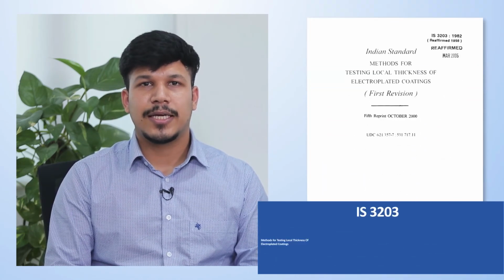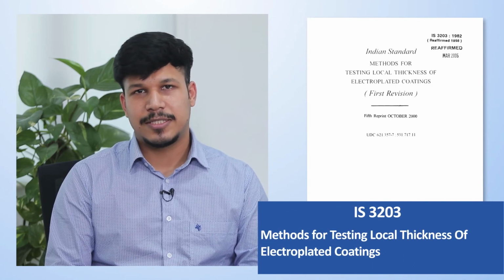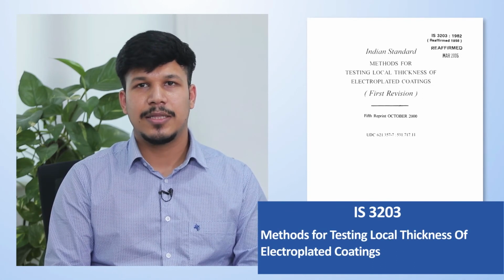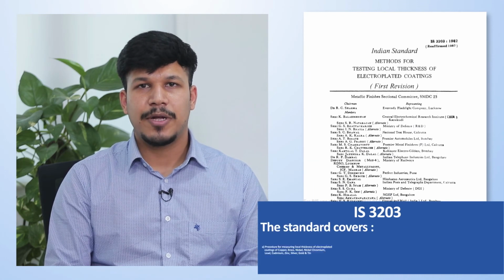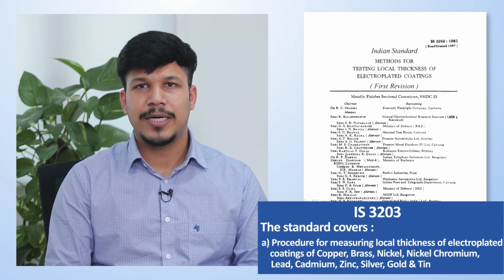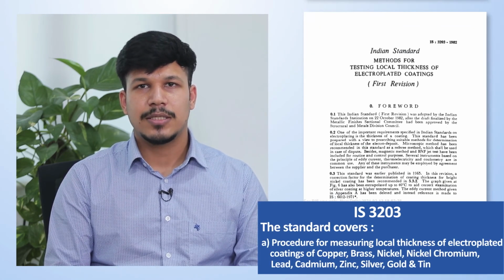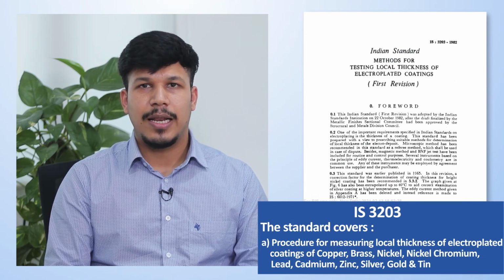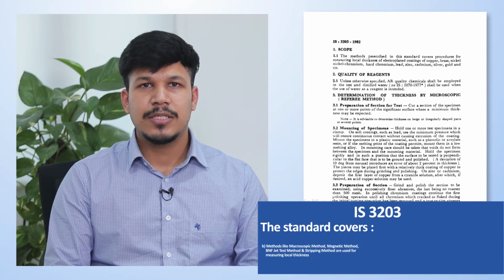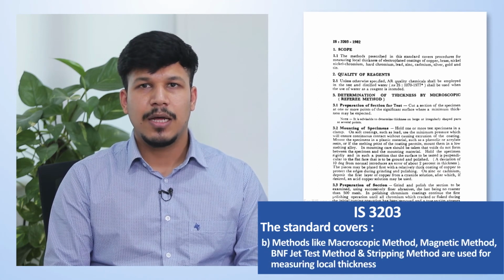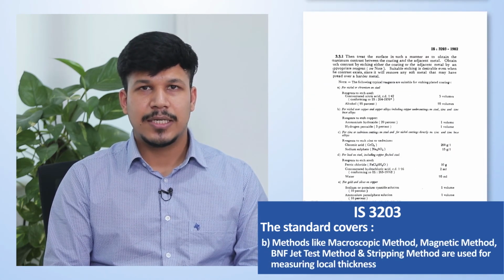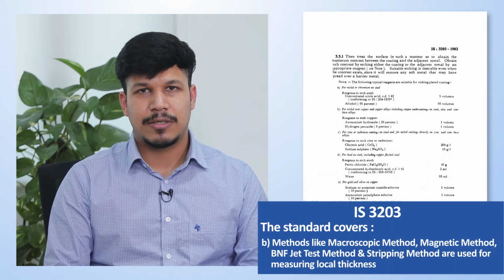The Indian standard IS 3203 is a test method standard, and methods prescribed in this standard cover procedures for measuring local thickness of electroplated coatings of copper, brass, nickel chromium, lead, zinc, cadmium, silver, gold and tin using various methods such as macroscopic method, magnetic method, BNF jet test method and stripping method, etc.